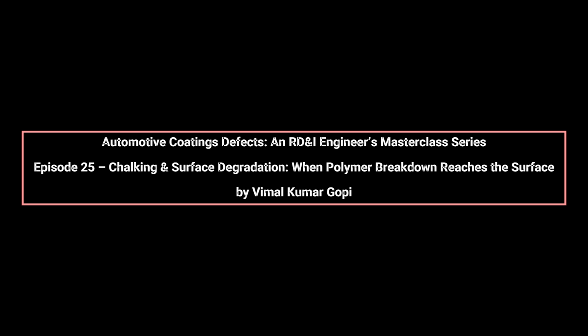In single-layer topcoats or colored clear systems, certain pigments provide partial UV shielding, slowing chalk formation. However, once the binder degrades, pigments themselves can be released, intensifying the chalky appearance. Cross-link density again plays a balancing role. Highly cross-linked polymers resist chemical attack, but degrade more brittly under UV exposure, leading to faster surface fragmentation once degradation begins. Lower cross-link density systems degrade more slowly, but may lose gloss earlier. OEM systems are optimized so that chalking occurs only beyond the intended service life.